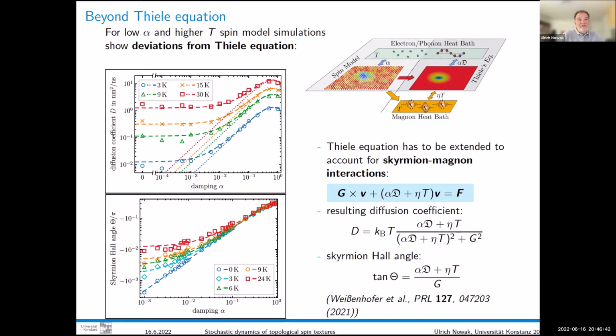And one can kind of repair that, by assuming there's another heat bath, namely the magnons, and you couple the Thiele equation to another heat bath, which is given by the magnons. But here, the magnon number is now temperature dependent. So at 0 temperature, there wouldn't be any magnons, but at higher temperatures, there are some. So in other words, this coupling here is temperature dependent. And one can repair the Thiele equation by assuming another dissipative term that depends on the temperature. And this eta here would be the strength of the coupling to the magnons. And then you can recalculate everything and then it works.